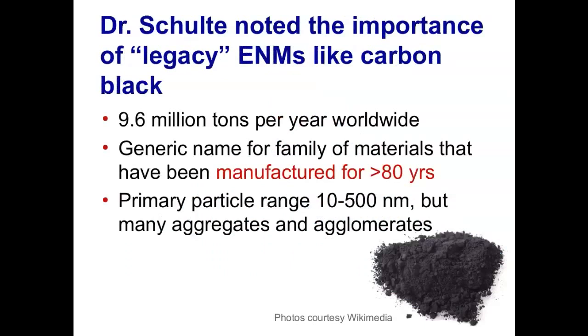Dr. Schulte noted the importance of what he calls legacy engineered nanomaterials, like carbon black. These are important materials for several reasons. One is they're manufactured in very large quantities compared to a lot of the other nanomaterials. Carbon black, for instance, 9.6 million tons manufactured worldwide. And also they've been manufactured for quite a long time, greater than 80 years with this particular material. Now they're not strictly what one would call an engineered nanoparticle of 1 to 100 nanometers in size. The primary particle range can be anywhere from 10 to 500.